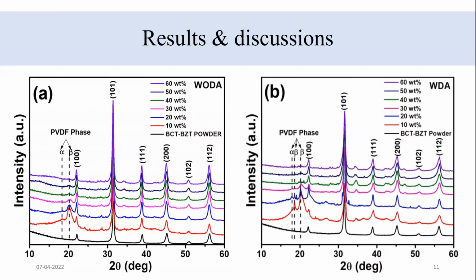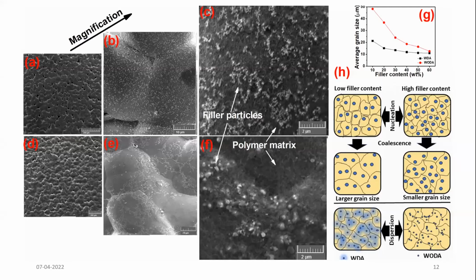Now these are the results. The XRD results are two graphs. One is without dopamine added, one is with dopamine added. As we can see, in the alpha and beta peaks, by adding dopamine, beta phase was enhanced. There are two sharp beta peaks with dopamine added, and without dopamine added, there is one beta peak. So beta phase was enhanced by using dopamine.